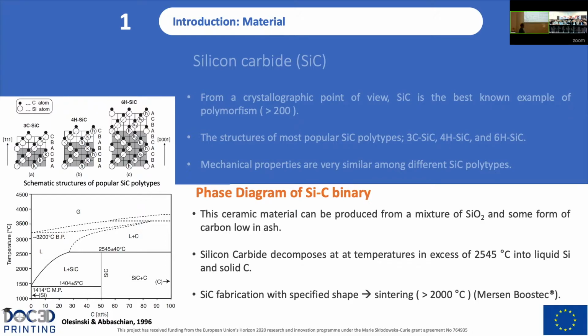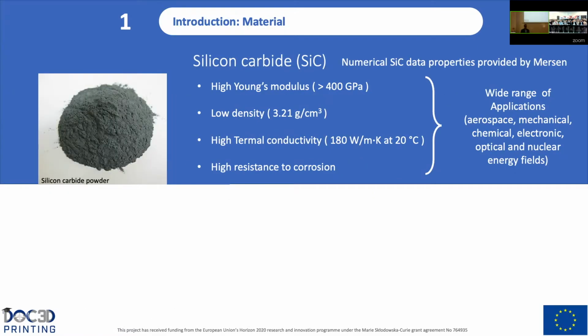Regarding the manufacturing of silicon carbide, the ceramic material can be produced from a mixture of silica and some form of carbon. And if we look at the phase diagram of silicon carbide, we can see that we don't have a melting point, but instead, silicon carbide decomposes into liquid silicon and solid carbon in excess of 2,545 degrees. And finally, silicon carbide fabrication is commonly made by a method called sintering, like for example at Mersen Boostec, the company involved in this project, which generally reaches temperatures in excess of 2000 degrees.